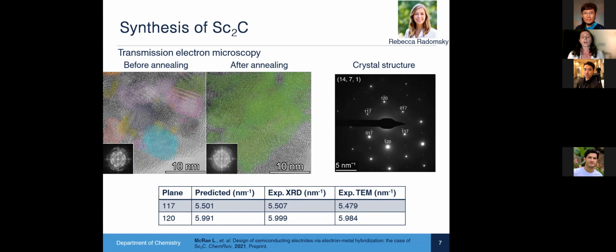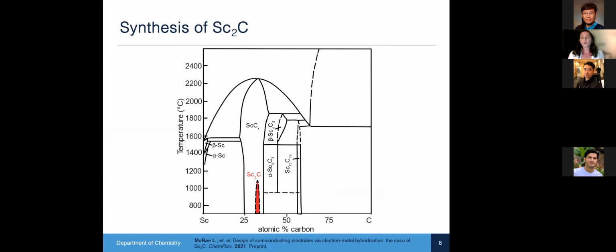And so we compared all of the predicted structure, the structure from XRD and the structure from TEM, and you can see that their lattice spacings all match up very well, which supports our predictions and again supports that we've made this layered discandium carbide and that annealing did in fact help this process. So now we're able to update the phase diagram to include this layered discandium carbide, and it sits in the middle of this large cubic disordered phase.